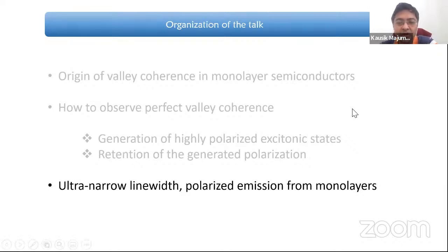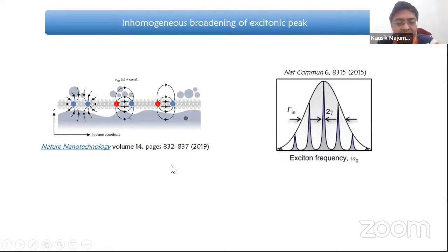In the last 4 minutes, I'll quickly talk about the other relaxation mechanism that I mentioned, where through a phonon you relax the excited states to the one state, and see what implications it may have. Typically, because monolayer TMDs are so thin, you have to put them on some substrate. So the luminescence or absorbance is bottlenecked by the inhomogeneous line width broadening. If you have a potential fluctuation on the substrate, it transfers easily, and you get something like this, while the true line width should be something like this. So the question is, what can we do to achieve the true line width in these material systems?